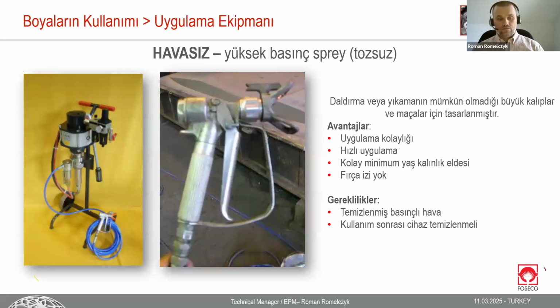Application methods or equipment for application, quite popular. This is the airless system. The prepared and diluted coating is pushed by high pressure through a special nozzle. So no atomization. It means that we don't have dust and fumes around when we apply the coating.